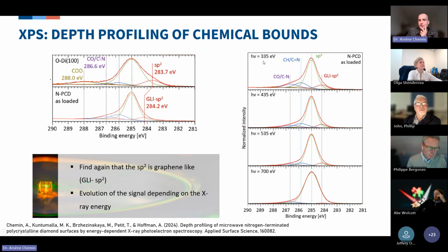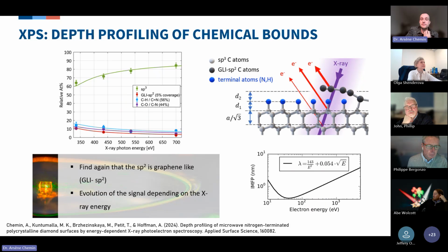And if you vary the excitation energy, from 335 eV to 700 eV, you will basically probe deeper and deeper. So in the case of this nitrogen terminated diamond at 335 eV, you can see a lot of signal coming from the surface states and a rather limited signal corresponding to the sp3 diamond bonding. But as you increase the excitation energy, you will lose more and more of the surface states and you will see more and more of the diamond below it.